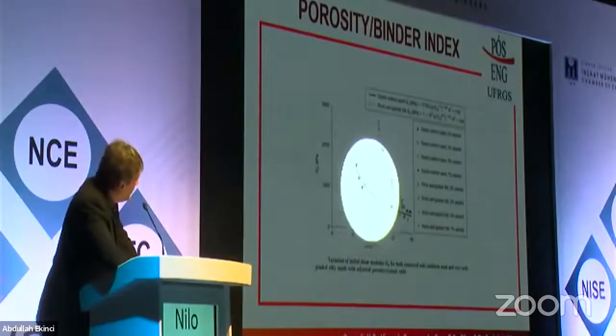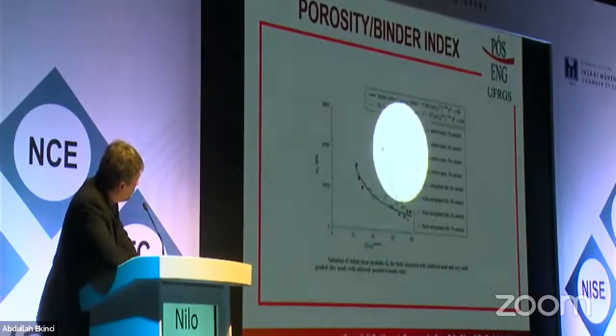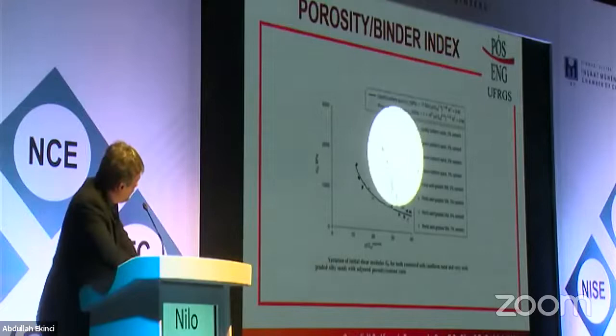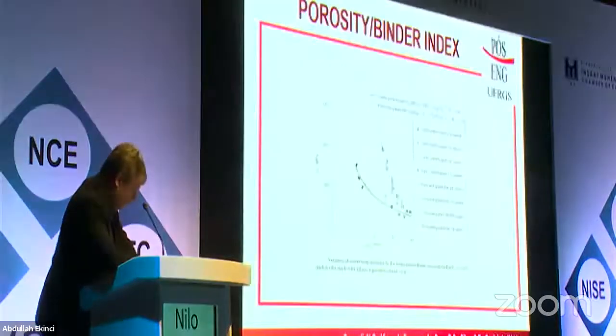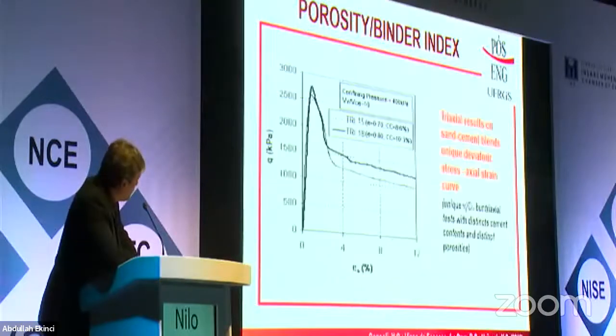So you have four different materials: these were sandy materials from Brazil, and this was a sandy material from Portugal. They have been tested by different people, but as I said, you have a unique curve for one material with one cement, and for the other you have another curve. But each curve is, as I said, controlled by this index.